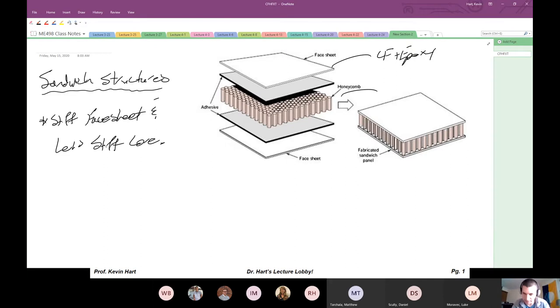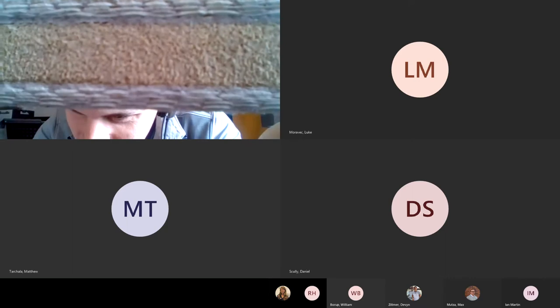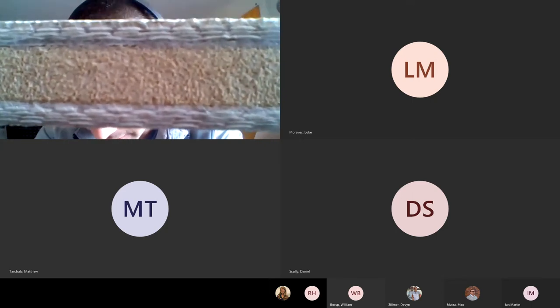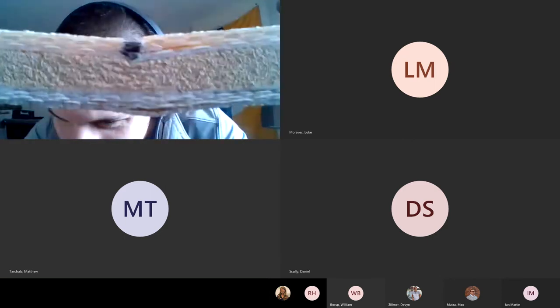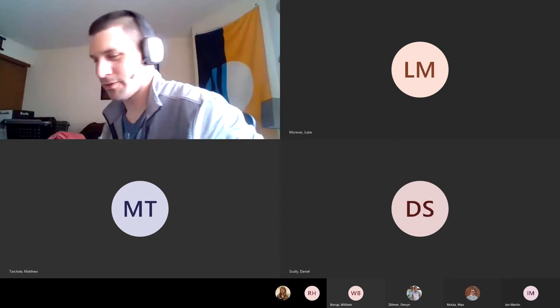Here's a good sandwich structure I have with me. You can sort of see the over-under woven pattern of the glass fiber — this is a plain weave glass fabric infused with epoxy, which is my face sheet, same on both top and bottom. The core is a medium density foam. The face sheets are maybe an eighth to three-sixteenths of an inch thick, and the core is about half an inch or a little over. This was tested in three-point bending, so you can see the failure modes in the face sheet, with some delamination on the tensile side.